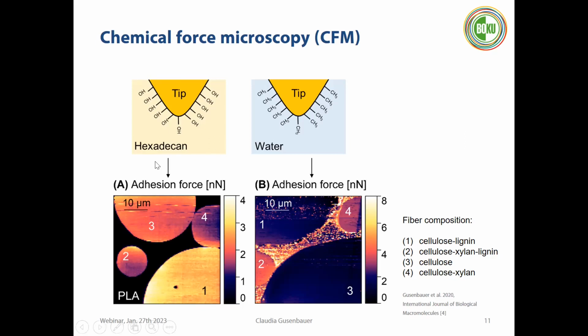And these adhesion maps are also captured with this really high resolution. So every time the tip touches our sample, we're recording structural information and also this adhesion map. For example, here we're scanning the cross-section of different cellulosic fibers, and we could see that the adhesion force is really depending on the composition of the cellulosic fiber. And we could map with high resolution not only the structure of these fibers, but also the polarity of these individual cellulosic fibers. So one of the fibers contained some lignin, one of the fibers did not contain lignin, and others had different compositions, and we could really follow the polarity changes depending on the composition of the fibers.